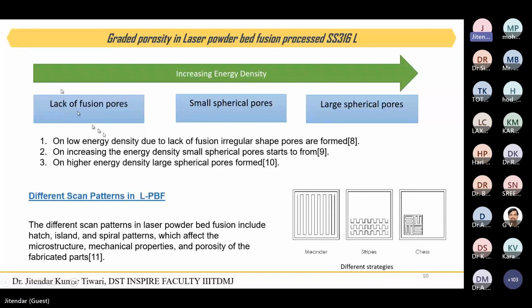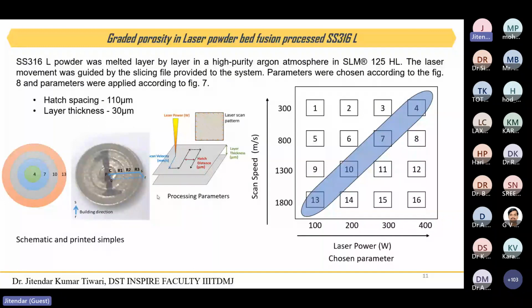So I hope you understood how we have achieved this kind of consolidation in porosity. Why I'm targeting this particular thing: in LPBF, if you want to make closed cell parts, it's impossible, because during closed cell printing, if let's say we are printing a closed sphere, once you print it, this whole powder will get entrapped inside that sphere. That is the problem. So to avoid that problem, we can utilize these spherical pores or keyhole pores as a porosity, and we can achieve a functionally graded kind of porosity.